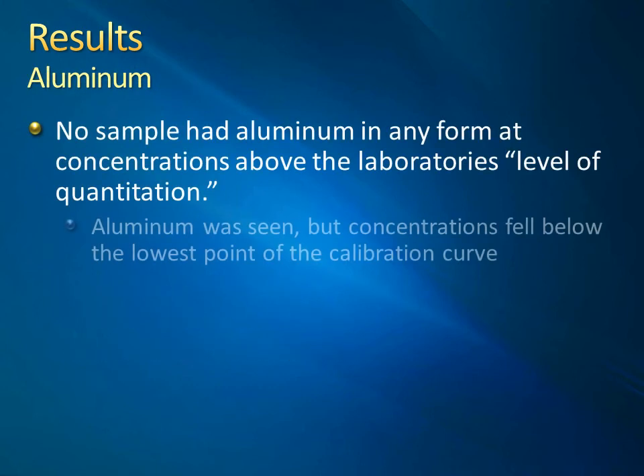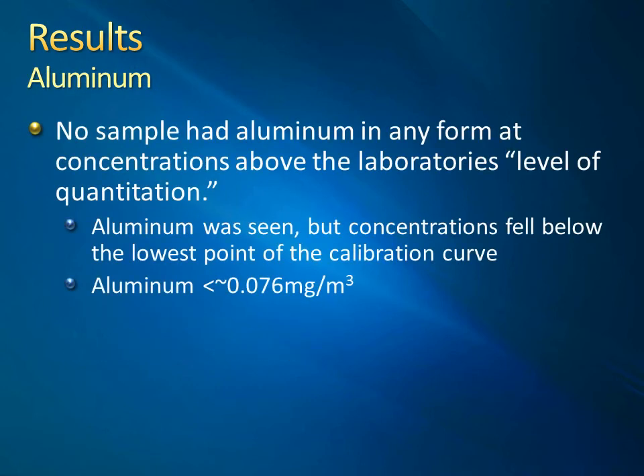For the aluminum samples, no sample had aluminum in any form at concentrations above the laboratory's level of quantitation. We had the same problem this time. Aluminum was seen, but it was below the low limit of the calibration curve. This result was also unexpected, especially due to the high operating temperature of the furnace again. It was reasoned that the excessive heat of the furnace would volatilize the aluminum to a much greater extent, but it simply was not seen.